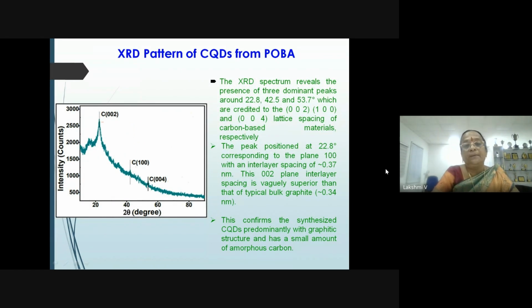XRD pattern, mainly we went through it to find out whether we have some graphitic structure. The XRD spectrum reveals the presence of 3 dominant peaks around 22.8, 42.5, and 53.7, which are credited to 002 plane, 100 plane, and 004 lattice spacing of carbon-based nanomaterials, respectively. The peak positioned at 22.8 corresponding to the 002 plane with an interlayer spacing of 0.37 nanometer. This 002 plane interlayer spacing is slightly larger than that of typical bulk graphite, which is just 0.34 nanometers. This confirms the synthesized CQDs have predominantly a graphitic structure and a small amount of amorphous carbon. So the graphitic structure will be further investigated through Raman spectra, sir, that I will be presenting in the next slide.